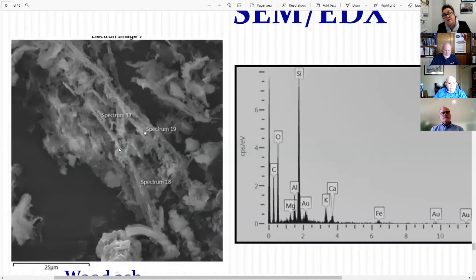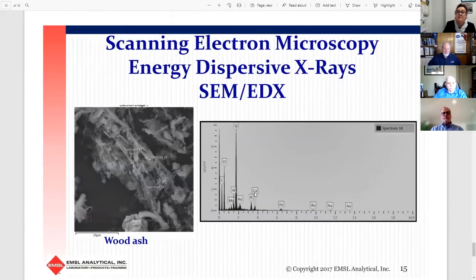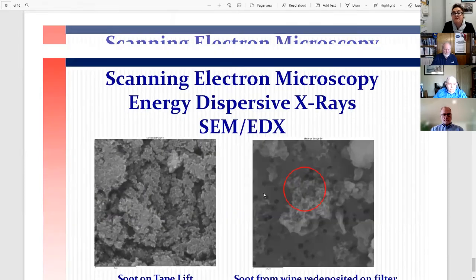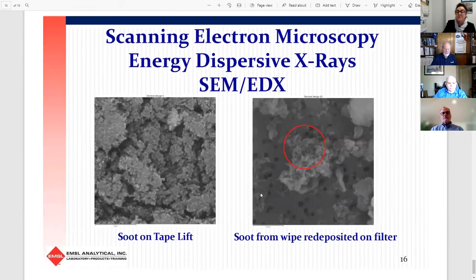So on the next page is the SEM image of ash, where you can still see, if you look carefully, the vegetative structure, but it is highly degraded and very brittle, and it's not easy to handle. And in the elemental composition, carbon goes down, and silicon is high because it's a phytolith, and it has aluminum, potassium, calcium. So why SEM? You don't need it really, just why not. For a normal analysis, but for a more comprehensive one, for comparison with sites, for example, it's a very, very useful technique. I'm not sure what I have on the next slide. Oh, okay. So what I have here is just showing how soot looks when you are putting it on a tape lift, and when you take it out of a wiper, you redeposit.